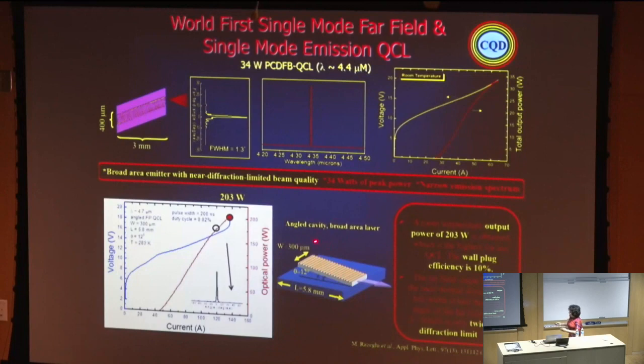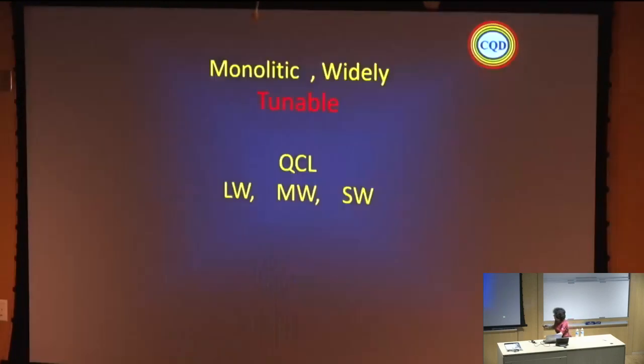We did again an angled cavity design, a new design, with only a 5.8 millimeter cavity length and only 300 micron width, with a 12 degree angle. As you can see, the far field is 3 degrees, 2 times the diffraction limit, single mode emitting, with more than 10% wall plug efficiency. 203 watts is coming out. 203 watts.